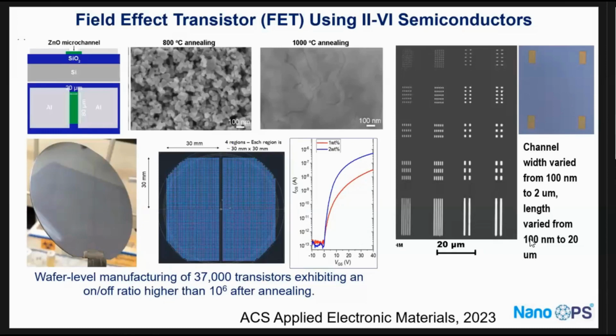These transistors are done on a wafer, and there are about 37,000 transistors. They're all discrete, not connected. They vary in size from 100 nanometers to 2 micron for the channel width, and for the length of the channel from 100 nanometers to 20 micron. We were very happy with the results. This was published recently, and we had a good on-off ratio, for example, for those.